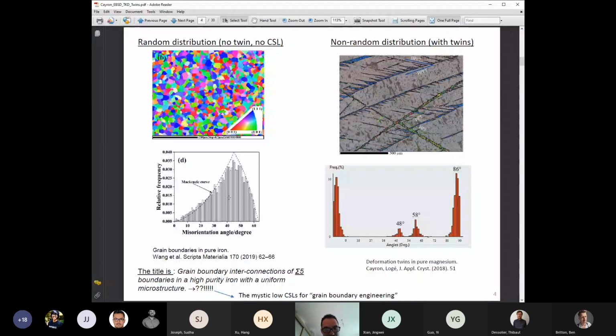And you will also notice that you cannot go up to 62 or 63 degrees, because of the symmetries. For example, if you find an angle of 70 degrees, you can reduce it by the cubic symmetries to a lower, equivalent rotation angle. That's why the curve stops at 62 degrees, something like that.